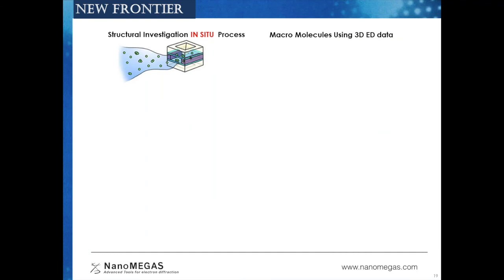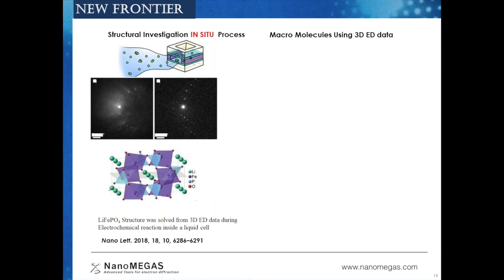Now, what next? What are the future promises for this technique, 3D electron diffraction? In the next few years, we believe structural analysis by 3D electron diffraction will make a major contribution, especially for in situ processes, as many in situ sample holders are now commercially available, and also for solving structures of macromolecules, and it will become more accessible to the whole scientific community. Let me show you the first example, where during an electrochemical reaction a new phase was formed, and it was possible to collect 3D electron diffraction data during this in situ chemical reaction. This is the structure of lithium iron phosphate, and you can see more details in these publications.